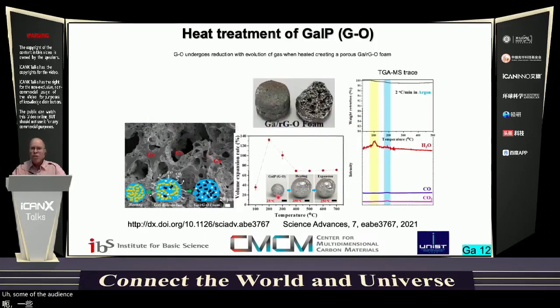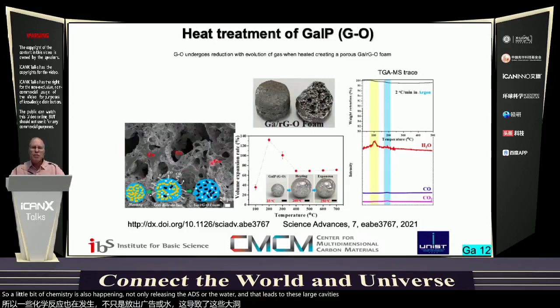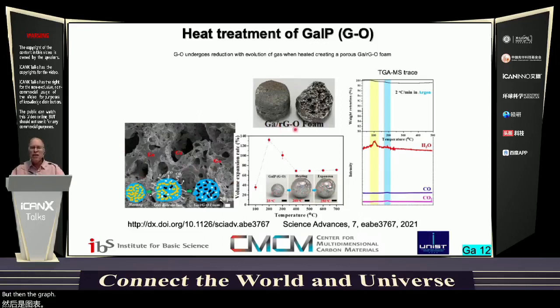Now, some of the audience might be aware that graphene oxide and also stacks of graphene oxide or graphite oxide contain water adhered to their surfaces. And so when we heat those, they typically evolve water, as is shown in this thermal gravimetric analysis mass spectroscopy trace, and carbon monoxide and CO2. So a little bit of chemistry is also happening, not only releasing the adsorbed water, and that leads to these large cavities being present. So we see a tremendous expansion, for example, during heating. But then the graphene oxide is reduced or deoxygenated. And consequently, it can be,